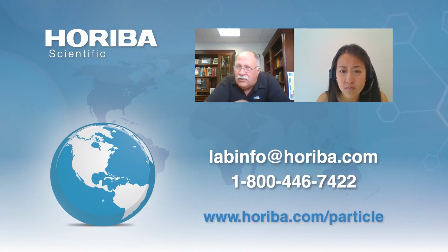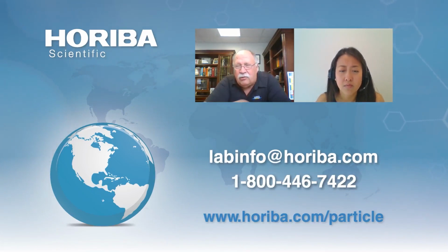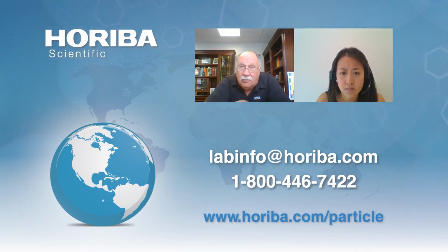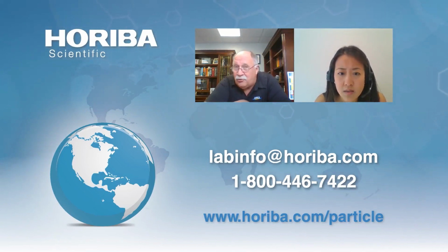What I would say, if it turned out that impurities were just the killer of all killers, we would probably line our chamber and our contact points in our mills and classifiers with silicon carbide. So if there was contamination, it would be silicon carbide. So maybe the answer is you can do it. You're just going to have to set your mill up properly to do it.